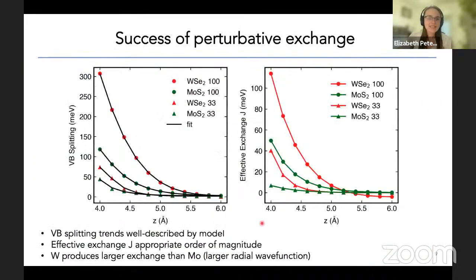And so I tried fitting my data to this model, looking just at the valence band splitting when I vary the Z position when I'm directly above the transition metal. And what I find is A, I can get very good fits to this data, and B, when I plot the exchange parameter J, and we zoom in on 4.4 angstroms again, I get exchange parameters that are on the order of tens of millielectron volts, which is the order of magnitude that I would have expected. And this is encouraging because it means that you can capture this and you get intuitive results for your exchange, and you get data that accounts for the orbital overlap and the out-of-plane magnetic moment.